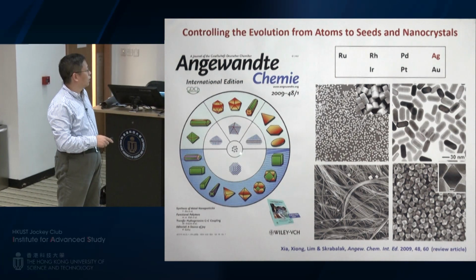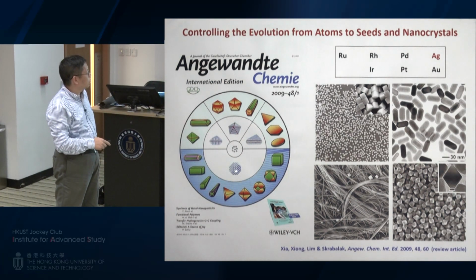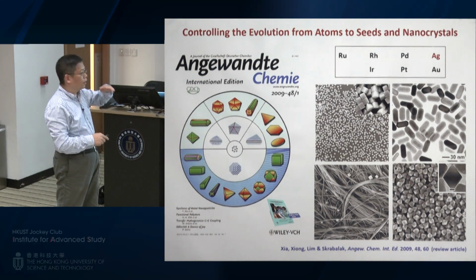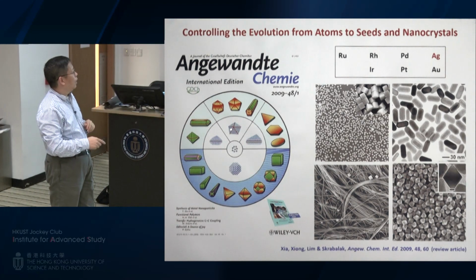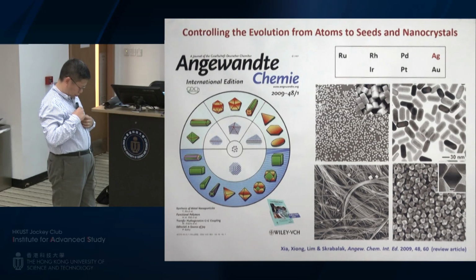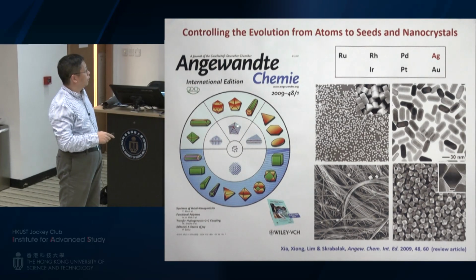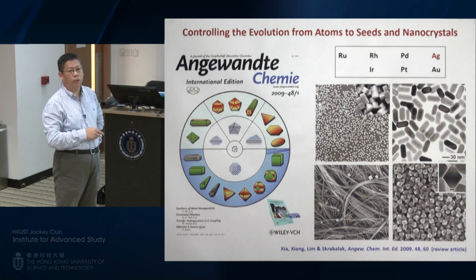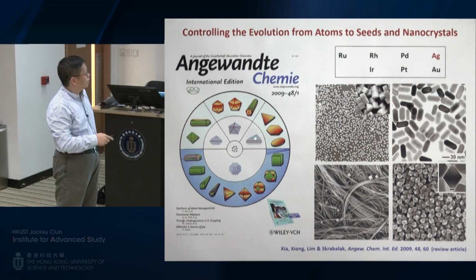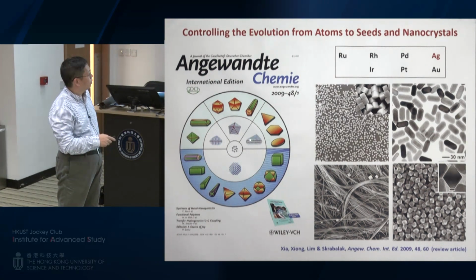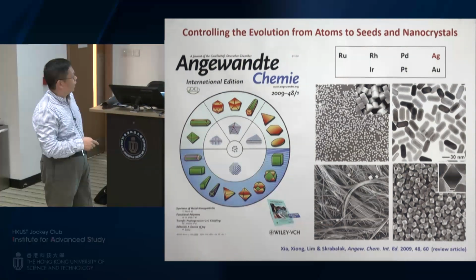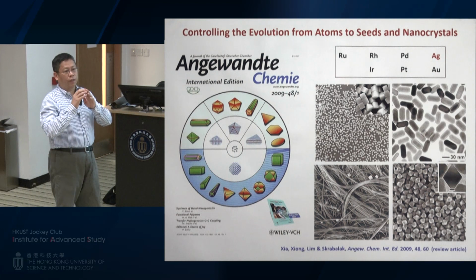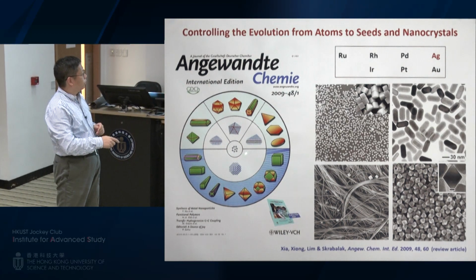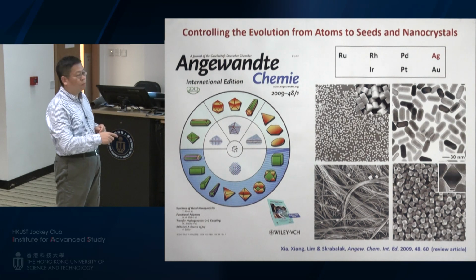So as a result, during the nucleation stage, you may form a single crystal seed. You may form a single twin seed; this red line over here indicates a twin plane in this crystal. Or maybe you can even have more than one twin defect being incorporated in the system. And this is a structure with other types of defects like stacking faults instead of twin boundaries. And anyway, you can see the system is going to get more complicated. Okay, you are going to have at least these 4 different types of seeds being formed.